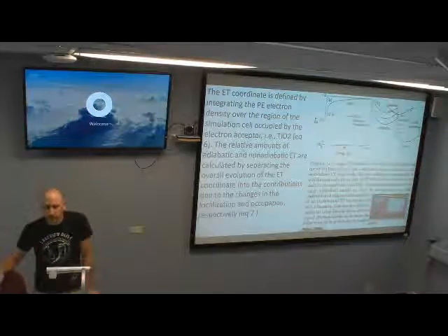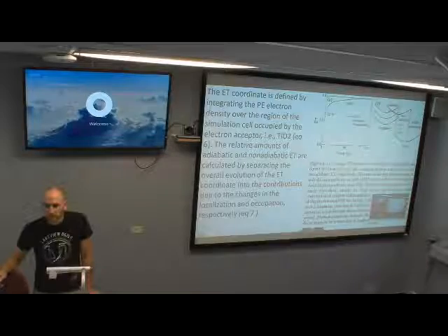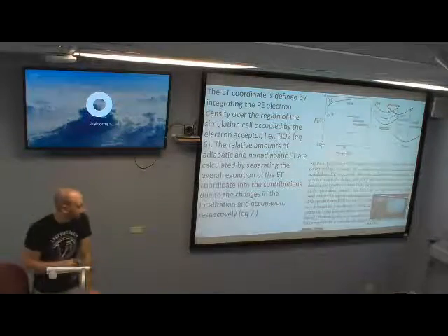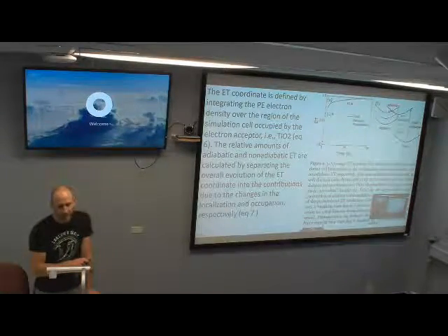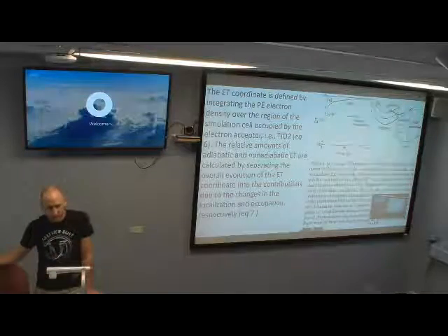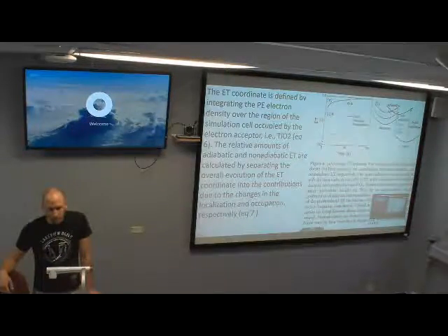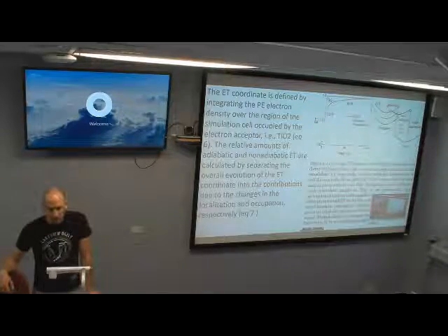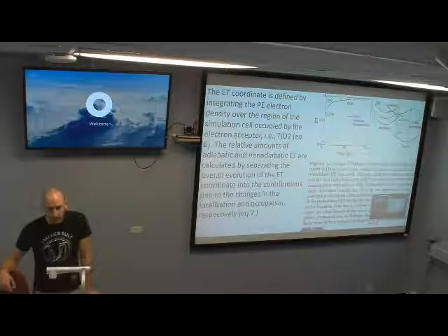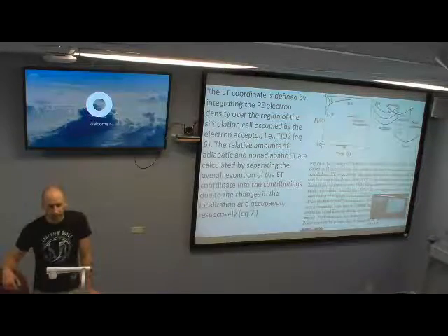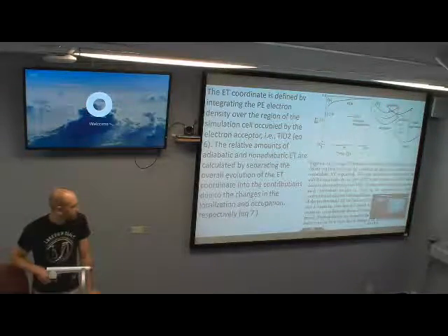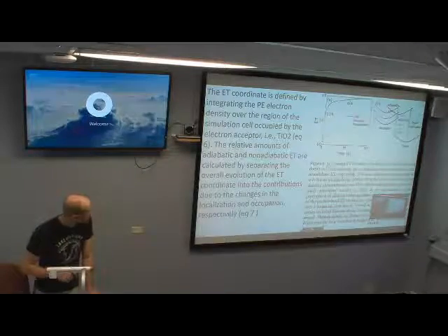First of all, the time scale is really very short, 100 femtoseconds. Yeah, but they end up having a total charge transfer within that 100 femtoseconds. So it's probably a random choice of these 500 samples from 3 picoseconds, because it looks like they don't need to go beyond 100 femtoseconds. So you really need a very short trajectory. Yeah, and this is averaged, I should mention too.